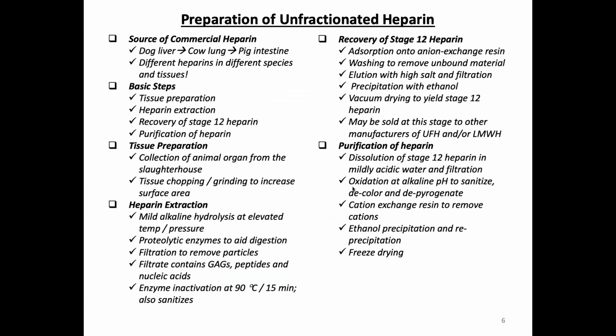One manufacturer might ask you to use 1 milligram heparin to give you 100 international units. Another manufacturer might ask you to use 1.5 milligrams of heparin to give you the same international units. Why is that? Because the amount of the heparin pentasaccharide in the chains of heparin might be different between different manufacturers. Right?